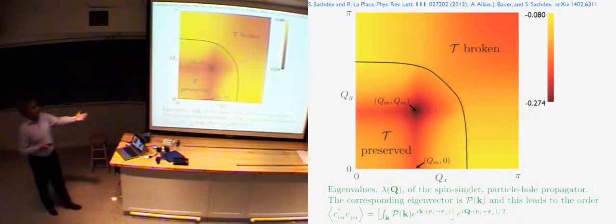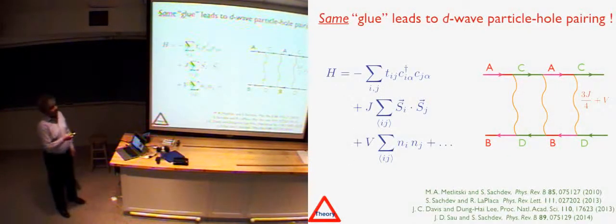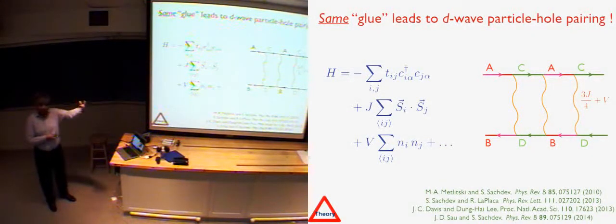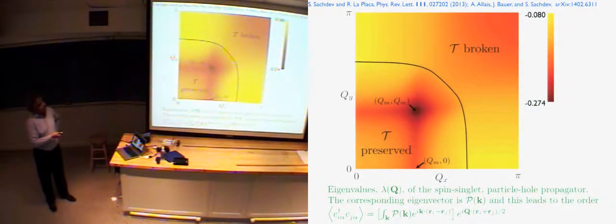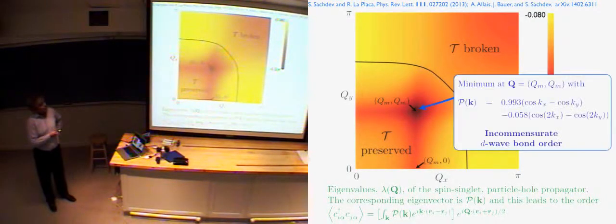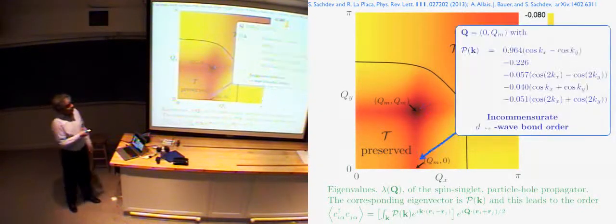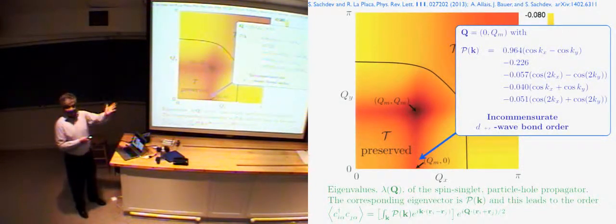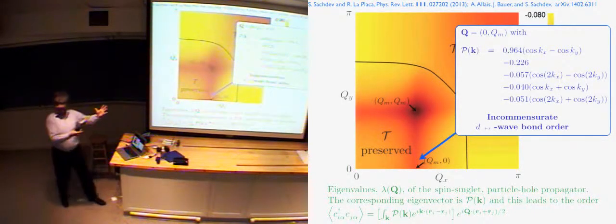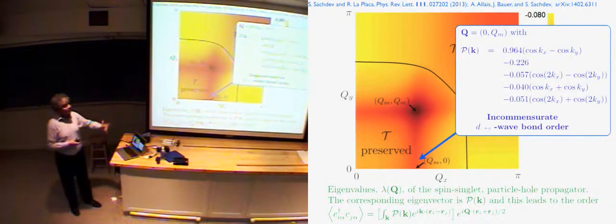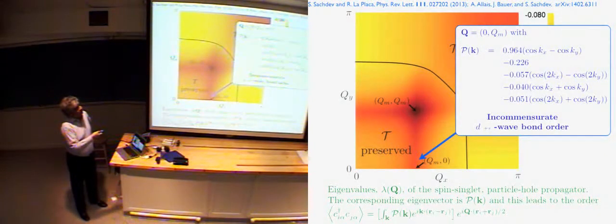Here's a more careful calculation where we solve the Bethe-Salpeter equations. We look at the eigenvalue of the particle-hole pair as a function of the center-of-mass momentum of the particle-hole pair, which is the wave vector Q of the charge density wave. When you do that, you find some different eigenvalue as a function of Q. The global minimum eigenvalue is at this wave vector Q_m,Q_m, which is actually not what's seen in the experiments. There we have essentially 100% D-wave. What's seen in the experiment is this other wave vector — that's the secondary minimum. Maybe a more complex calculation would make that the global minimum. But already this calculation showed that if I look at the eigenfunction of the particle-hole pair at the experimentally observed wave vector, it's 10-20% S but mostly D — still D for the same reason.